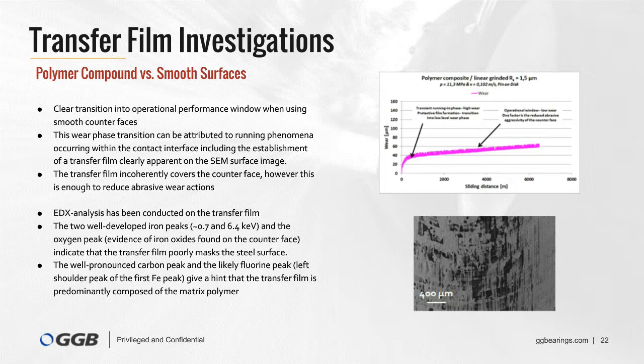Looking on the right side, we see the wear readout of the experiment. We see that a smooth counterface leads to low wear during the operational performance phase. Again, we can explain this by the formation of a transfer film. And we see this formation of the transfer film in the SEM image below the graph. The dark areas of this image are the transferred polymer on the steel surface, and the light areas of this image are the initial steel counter surface.